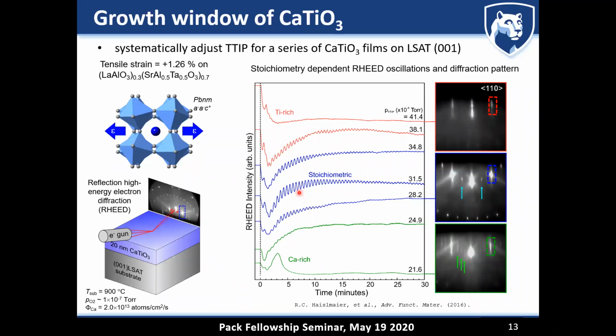And how did you deal with the evaporation rate of calcium? Calcium does not evaporate at 900 degrees C fast enough. We did not have any problems with calcium. I think the reason is that calcium stays long enough on the surface, and as soon as it sees a titanium-containing metal organic molecule, they do a chemical reaction forming calcium titanate.